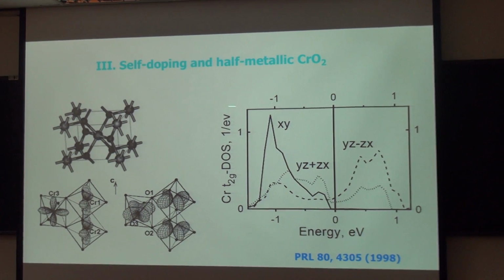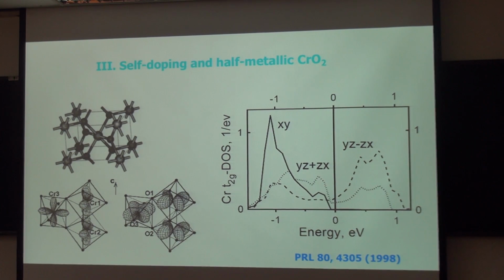Unlike the previously mentioned insulating systems, for transition metal oxides this is a very rare example. That is metallic. This is a half-metal, which means in this material the carrier is fully spin polarized. This material has a very simple crystal structure. It has a rutile crystal structure. And the chromium ion has two electrons.